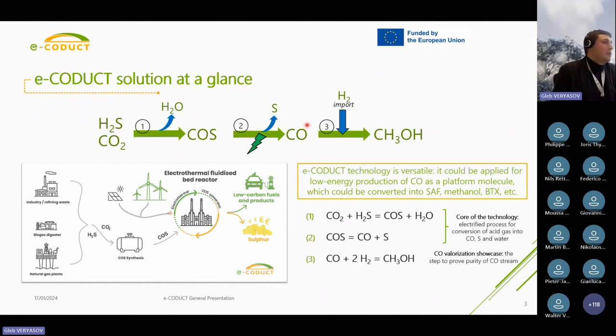Carbon monoxide is in principle a versatile platform molecule which could be used, for instance, in the Fischer-Tropsch process, for aromatics production, for methanol production, and for paraffins up to sustainable aviation fuel grade. In our case, we selected methanol production as a very well-known reaction, and we use a commercial catalyst with hydrogen import just to showcase that our carbon monoxide is convertible, so that we could really valorize it.